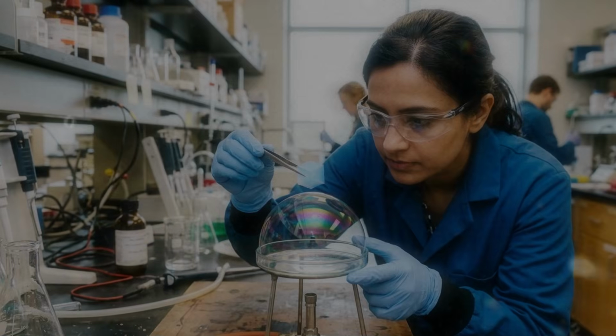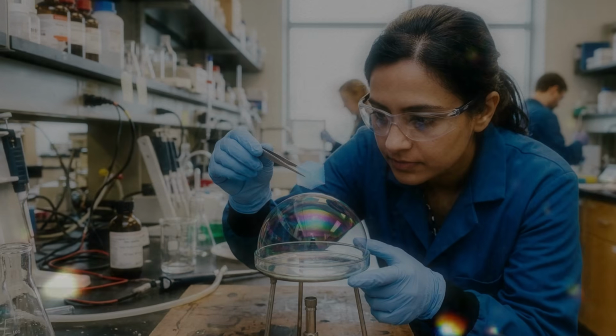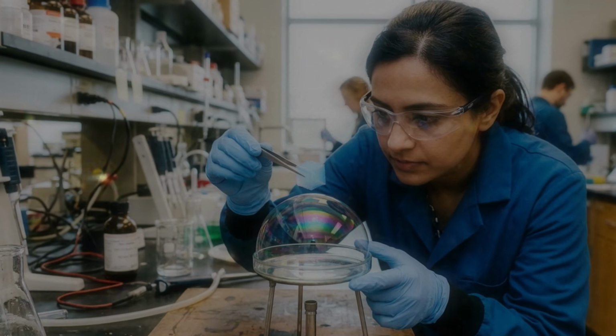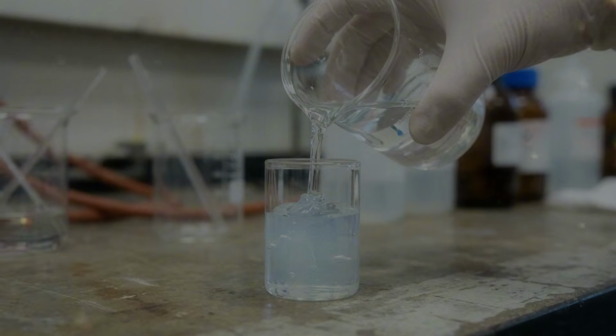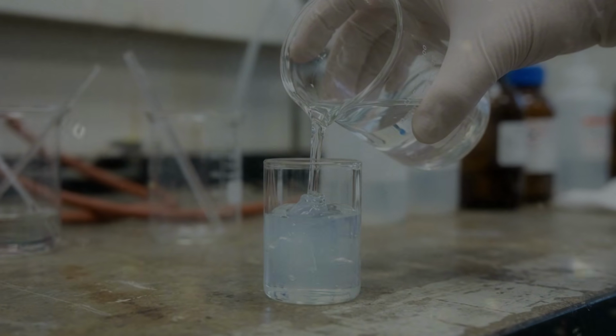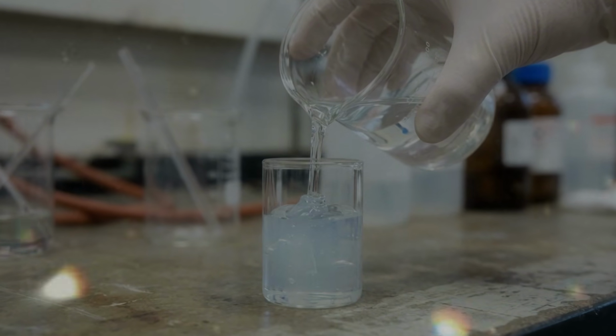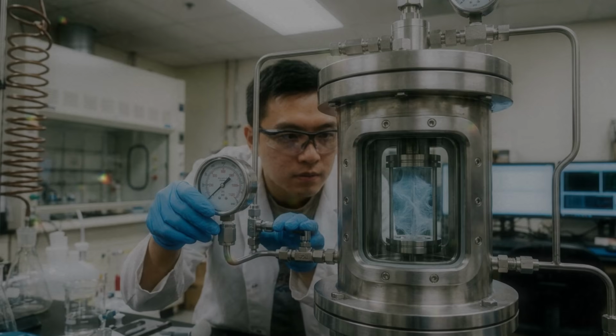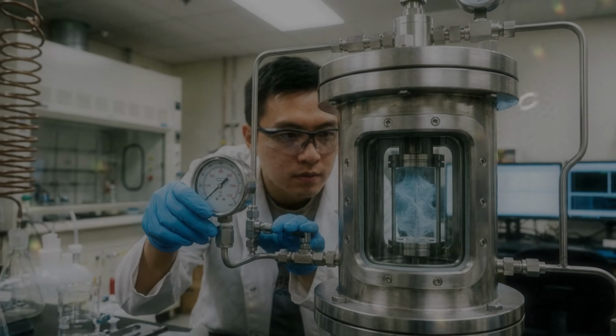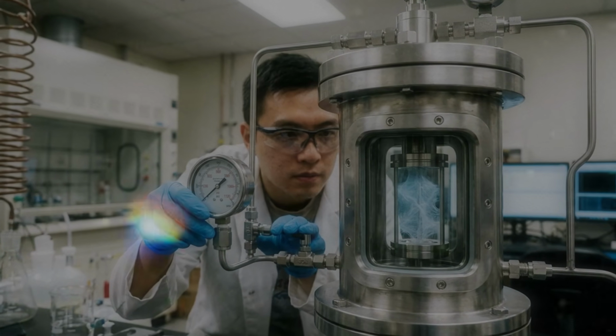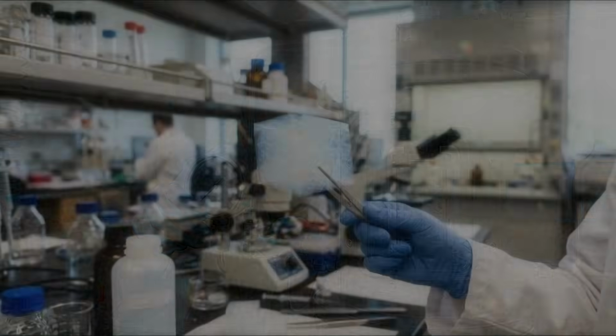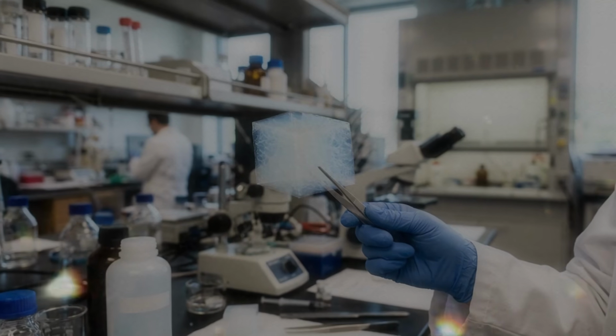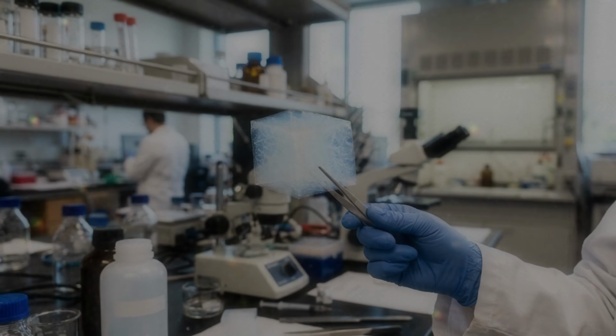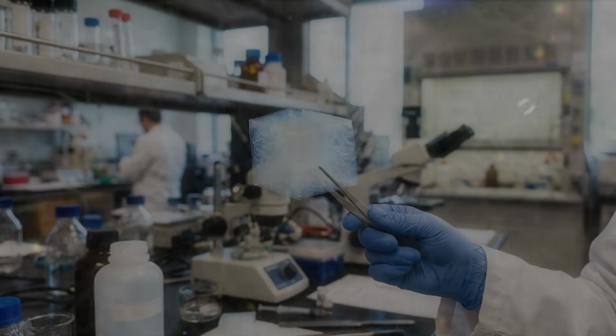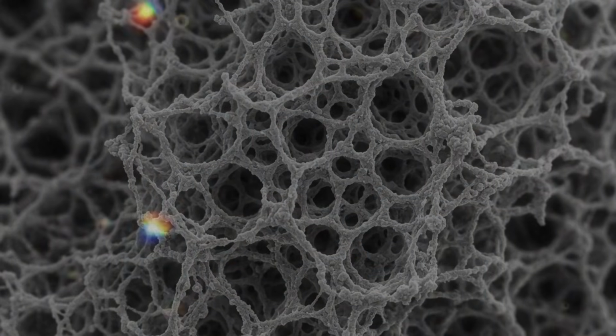The receding liquid behaves like countless tiny hands pulling inward on every part of the structure. A wet towel survives ordinary drying because its fibres are large and flexible. A delicate gel network may not. As the liquid retreats, the pores can collapse. The sample shrinks, hardens, and sometimes cracks into pieces. The result is called a xerogel, a dried gel that has lost a significant amount of its original pore structure.